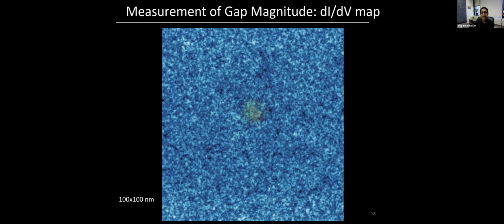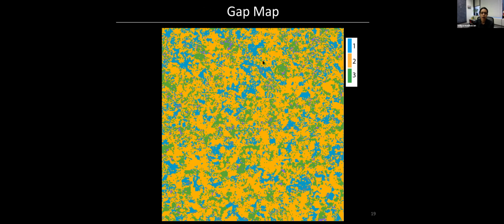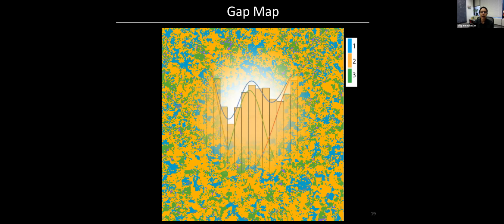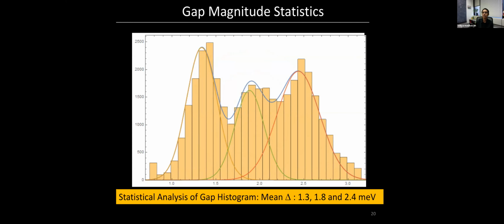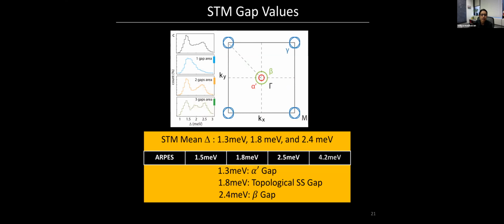So let's ask if we actually see this. And so we can go and measure the gap at each position. And as usual, this is what I would call a gap map. But the most important thing here is that there are regions here where you see 3 distinct gaps. And if I do a gap histogram, this is a statistical analysis from thousands and thousands of spectra, then you can see that we do have 3 distinct gaps, although the histograms are broad because of inhomogeneity. The gap values have mean values of 1.3, 1.8, and 2.4 meV. The reason this is important is because then you can compare to ARPES, and you can assign this particular low energy gap at 1.3 meV to the alpha pocket. This is the topological surface state, and this is the beta pocket.